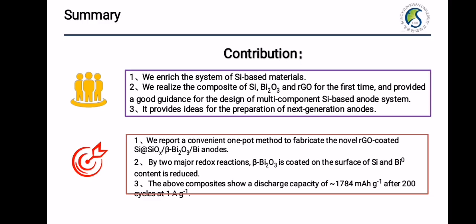We report a convenient one-pot method to fabricate novel reduced graphene oxide coated silicon@silicon oxide@beta bismuth oxide@bismuth anodes, and by two major redox reactions, the beta bismuth oxide is coated on the surface of silicon and the bismuth content is reduced. The above composites show a discharge capacity of about 1784 milliampere-hour per gram after 200 cycles at 1 ampere per gram.